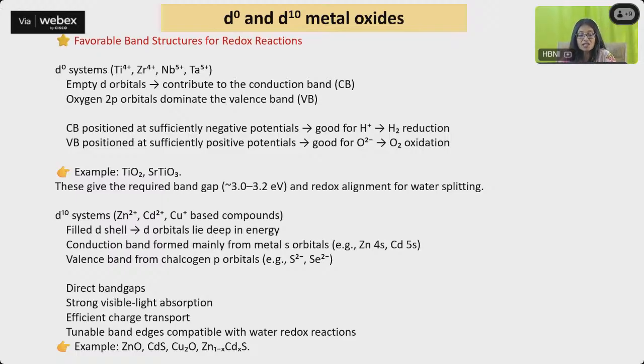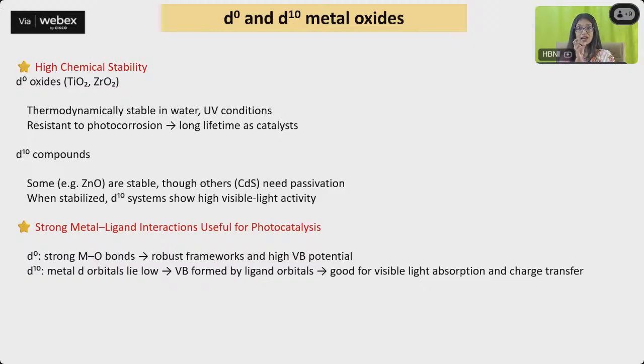So all these materials like zinc oxide, cadmium sulfide, copper oxide, because they are d10 systems, they are again very good photocatalytic materials. These kinds of materials also have very high chemical stability. Like d0 oxides such as titania, zirconia, they are thermodynamically stable in water and also under ultraviolet conditions, and they are resistant to photocorrosion. So they have a very long lifetime as catalysts, which is again a very good point when you're talking about photocatalysis. D10 compounds, some of them are stable, but some like cadmium sulfide will need passivation. When you're able to stabilize this, they will show high visible light activity.